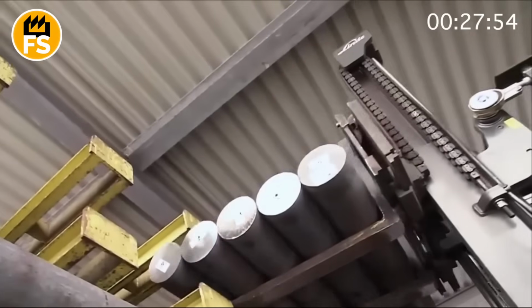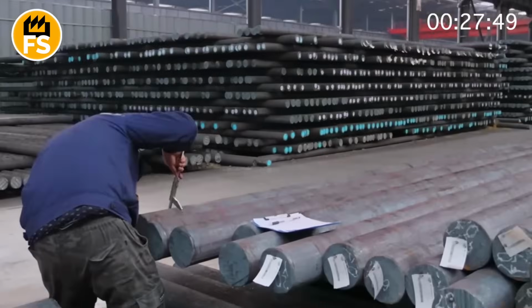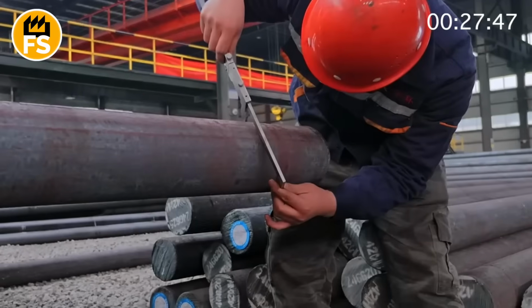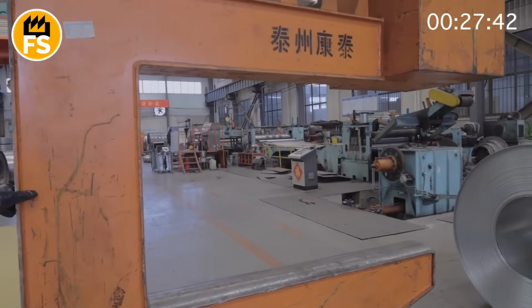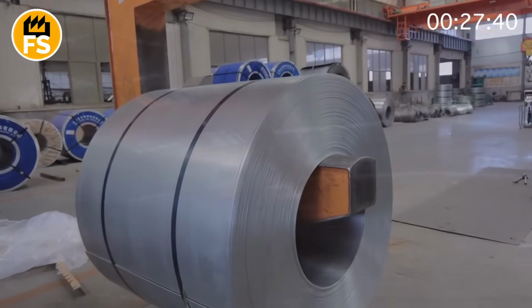This is how they search for cracks and inclusions of foreign materials within the billets. The system builds a 3D map of defects with an accuracy of 1/100th of an inch. If it finds a saboteur, the billet is marked with red paint and sent to metal hell for remelting.